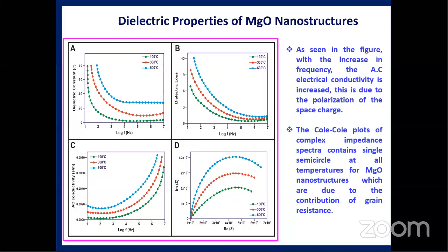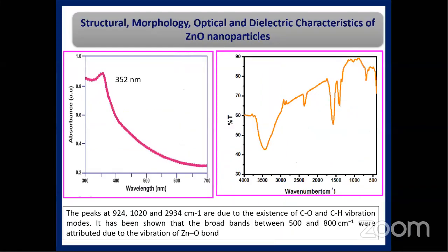And then for figure C, you can see the AC conductivity of this MgO nanostructure. AC conductivity increases with increasing frequency, and AC conductivity also increases with increasing temperature. And this one is a Cole-Cole plot. The complex impedance spectra contain a single semicircular arc at all temperatures, 100, 300, and 600, because in the MgO nanostructure this is due to the contribution of grain resistance.